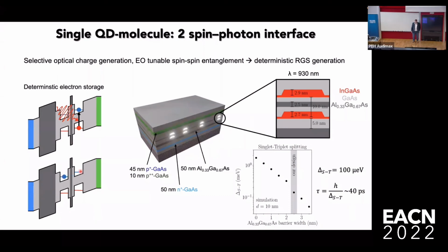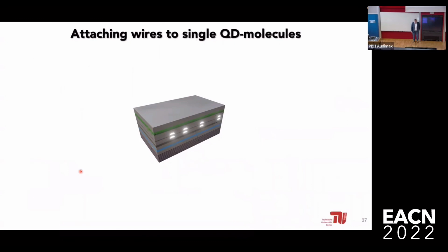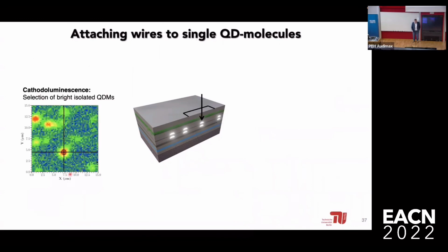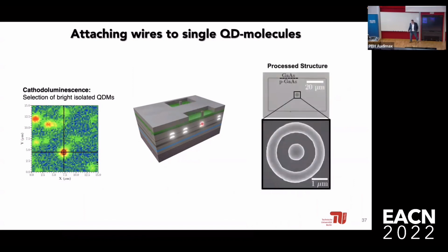So this sounds challenging. It turned out it was challenging, but we managed to do it. So let me show you what the device looks like, a real device. We first send the sample to Berlin, and Stefan Reitzenstein is in cathodoluminescence finding single molecules. There's one of them. He then, around this single molecule, is writing an annular Bragg mirror. So that's an annular Bragg contact to strengthen the coupling with that single molecule. There's an example of that, and there's a picture of the device. It's actually only 2 periods of this grating. That's enough to get us about 20 to 30% coupling efficiency.